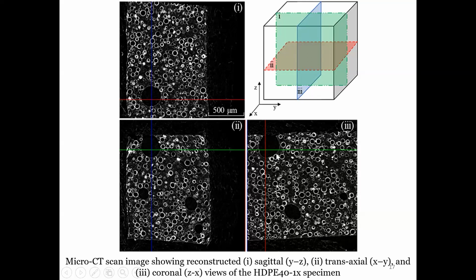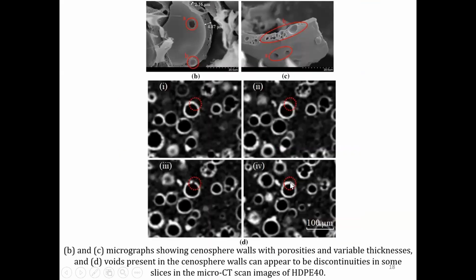But there is one particular thing we all have to really remember about micro CT, and I'm going to show that with the help of this slide. Here the fly ash cenosphere wall is also porous. You can see the porosity within the walls. In micro CT, whenever you take it, there is one misinterpretation; rather, we can misinterpret. Micro CT gives an actual picture, but how we misinterpret is, this is 1, 2, 3, and 4. Behind 1 comes 2. Micro CT slices a particular material system into thousands and thousands of layers or slices. So 2 is behind 1, 3 is behind 2, 4 is behind 3, and these are apart by very few microns. So typically in the same zone, we have different slices.